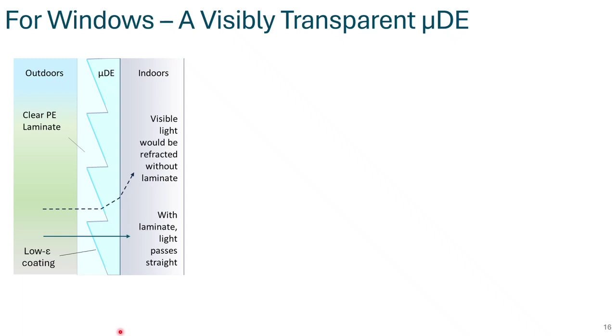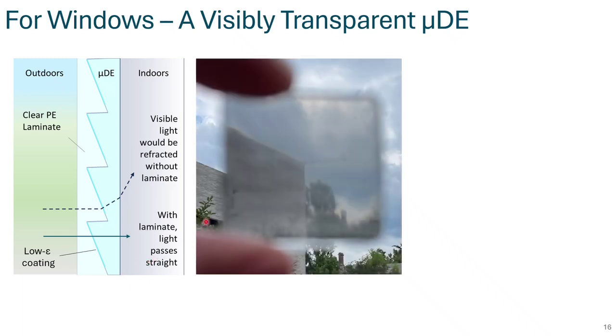Unfortunately, it's not that easy because right now we have a pattern on the front side and a flat surface on the other side. With the refractive index variation, it results in the turning of the image transmitted through the sample, as you can observe on this photo. You see that the background and the transmission are slightly shifted.